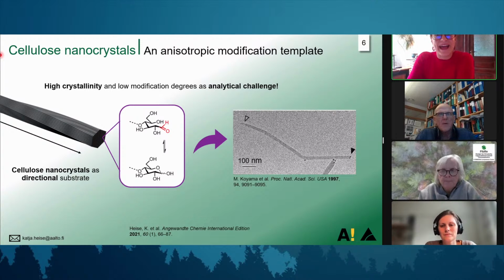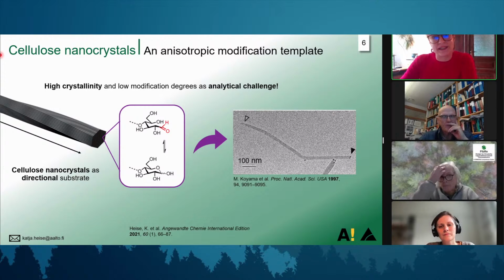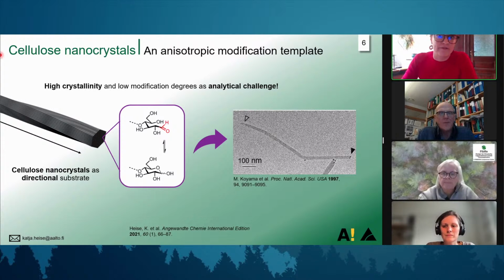Yeah. This really depends on the stability of your samples. As I mentioned, you have a basic electrolyte, and what we observe, for example, in certain cases when we have esters, is that we actually hydrolyze our ester bonds. It really depends on your sample. I'm sure that Alistair has probably tried out many different conditions, and the optimum they found was really 65 degrees, as a compromise between viscosity and sample stability. But maybe you could try it depending on what you have. Yeah. It's certainly an idea to try if you have pulp samples, for example. Okay, thanks. Yeah, thank you.